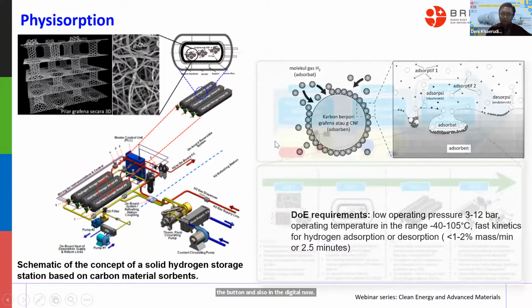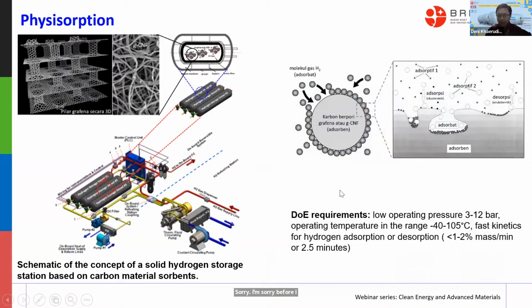I'm sorry, before I go further, this is just to remind you of the DOE requirement for the ideal condition of storing hydrogen in the solid state, like a low operating pressure, if possible about 3 to 12 bar. But there are many papers, which I will show you later in the next slides, with very low vacuum or very high pressure, up to 100 if I'm not wrong. And then the temperature range, if possible, about minus 40 to 100 degrees C, because this range of temperature is very common in industry. So this is what the DOE targeted. Why? That's the reason. And also the fast kinetics, regarding adsorption and desorption, if possible about 1 to 2% of mass per minute, or 2.5 minutes.